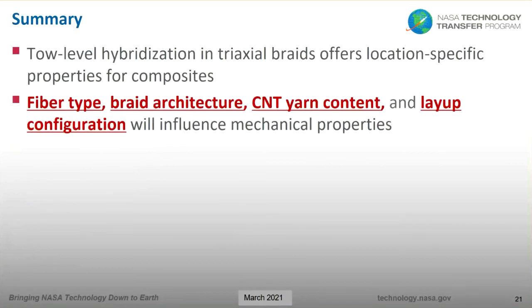Preliminary findings with this hybrid braided composite were very promising, showing that the tow level hybridization for use in a triaxial braid is able to offer location-specific properties for your application. In my particular study, I only tried out one type of carbon fiber and a single type of resin. So the properties for this type of composite could vary considerably according to the fiber type or the tow size of the carbon fiber that you use. One should take that into account whenever you're trying to identify the appropriate carbon nanotube yarn concentration to use.